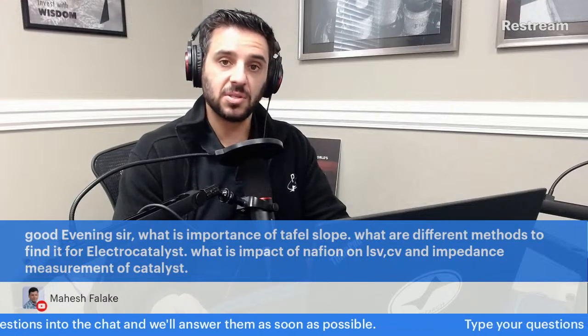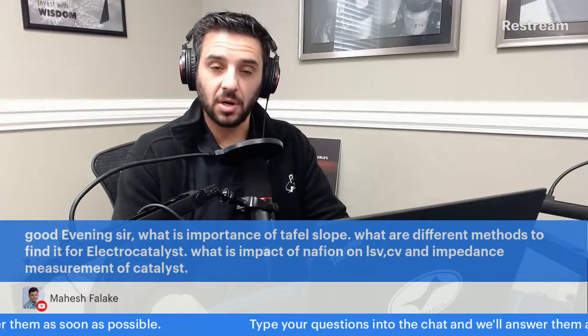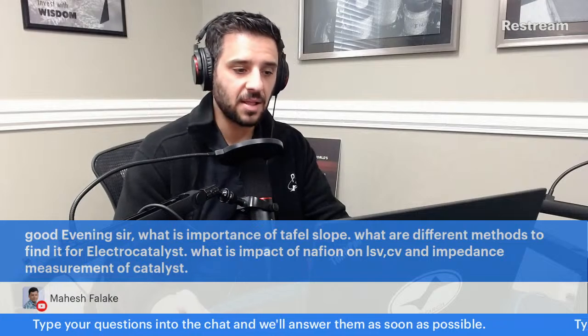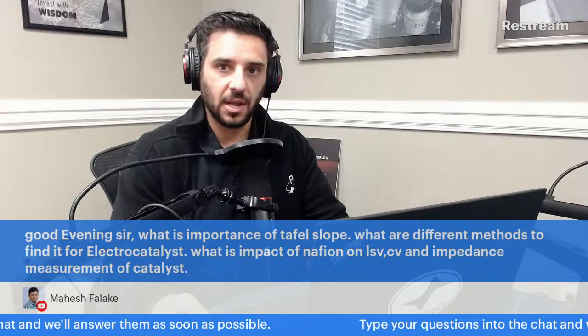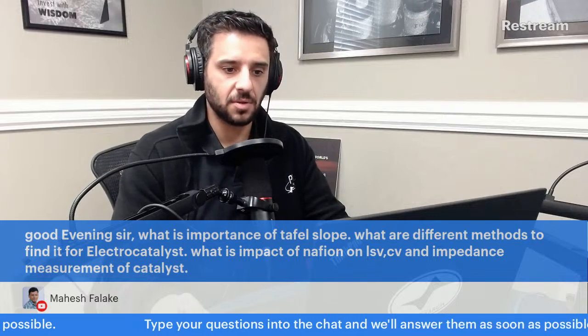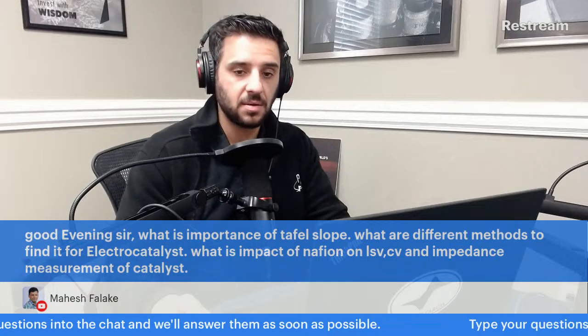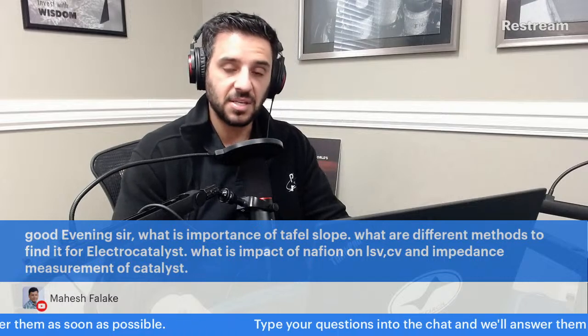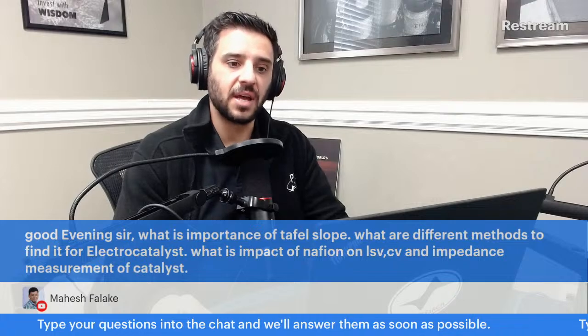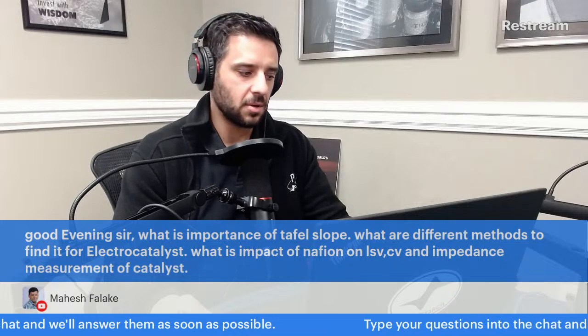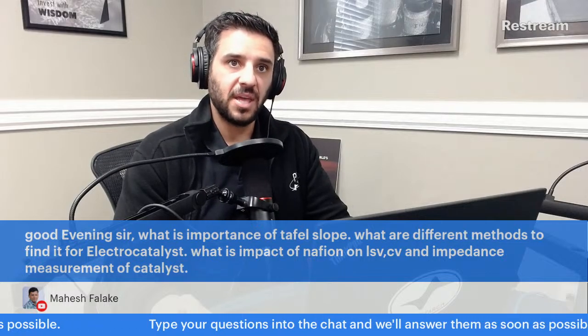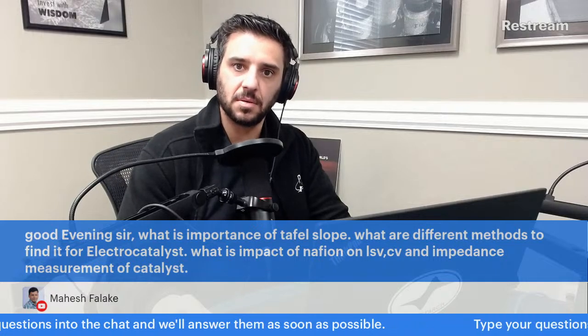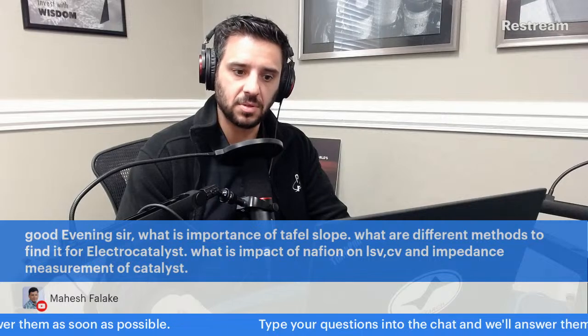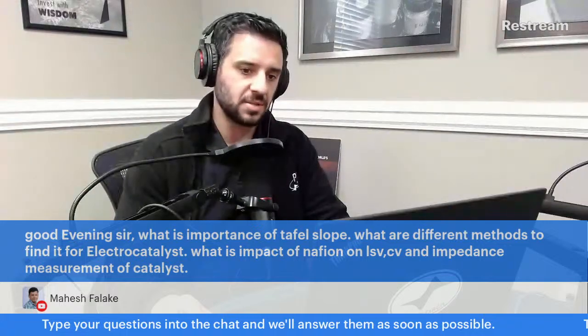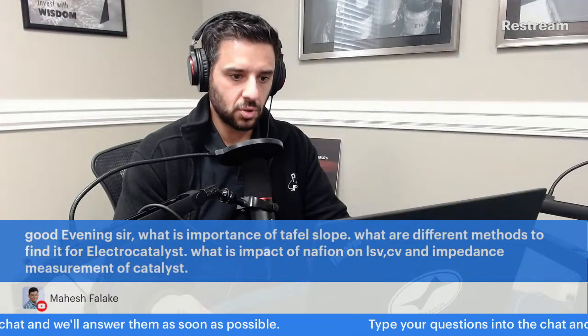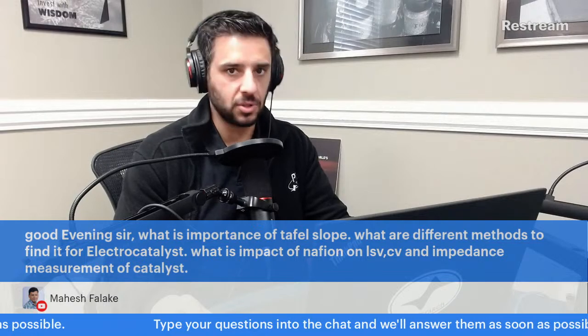The other is to simply assume in some situations that the bulk of your current is the result of kinetic processes. It's not always exactly the case. It's a dangerous assumption because there's non-Faradaic processes. There's other diffusional things going on often. So to assume that the number of milliamps or amps or microamps you get is all kinetic current can be a dangerous assumption, but it is technically possible to do Tafel analysis. If you don't have the ability to rotate your electrode, if you take current in a place where it's mostly kinetic processes occurring, it is perhaps reasonable to then use something like CV or bulk electrolysis as a method to find the Tafel slope or do a Tafel analysis.